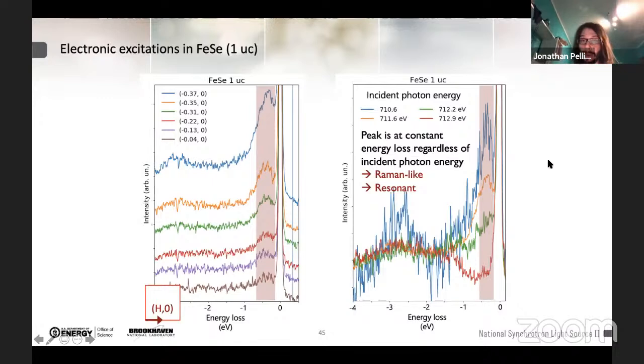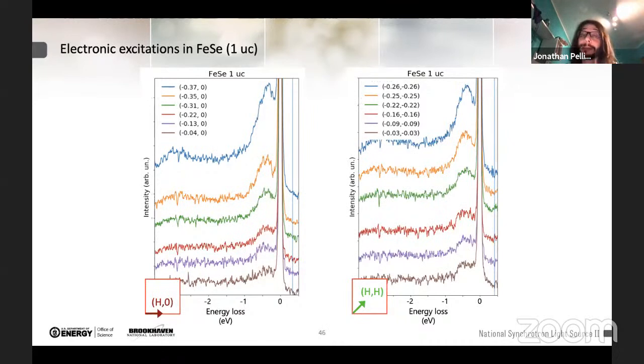The next step was to investigate the RIXS spectra along the diagonal crystallographic directions. And here on the right-hand side, I'm plotting the RIXS spectra that we observe, which further corroborates what we have observed along the H0 direction. So we have a pretty strong excitation at around 350 to 400 millielectron volt, and this excitation doesn't disperse as a function of momentum.